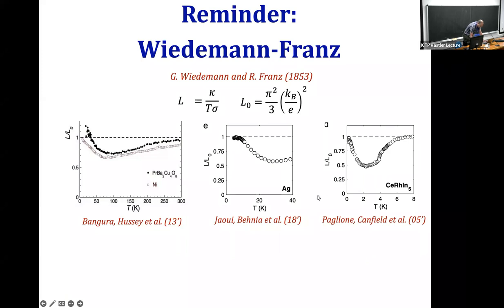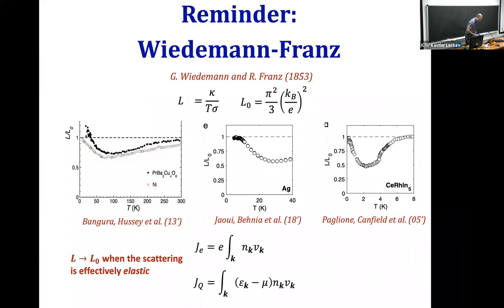So it's really a quantitative prediction. Okay, and what's the origin of the Wiedemann-Franz law? It's basically elastic scattering. It comes very naturally out of the Boltzmann equation when the scattering is elastic, and the argument is very, very simple. The idea is that at low temperature, both the thermal conductivity and the electrical conductivity are basically carried by electronic quasi-particles. And to get a resistivity of any kind, you need to relax either the electrical or the thermal current. Here's the expression for the electrical current in terms of the quasi-particles, and here's the thermal current. Now, if the scattering is elastic, it cannot modify the energy of the quasi-particle.